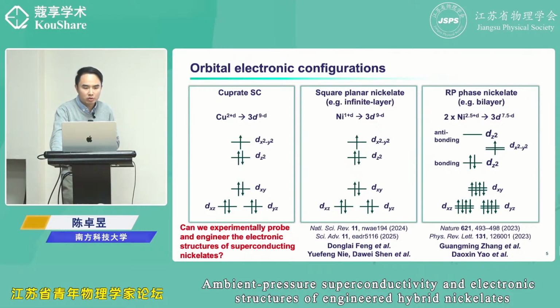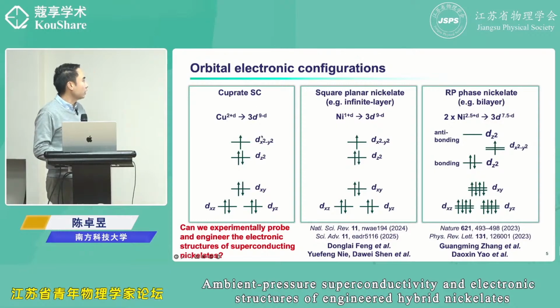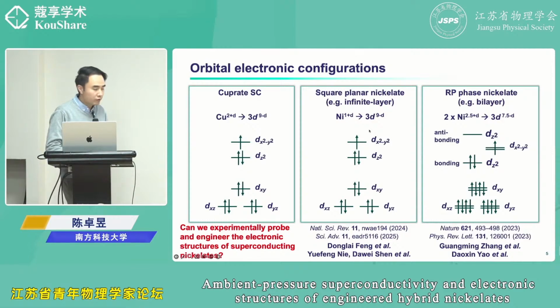Coming back to electronic structure, cuprate and the square planar nickelates are quite similar. This is 3d9, and you can see dx square minus y square is at the top. And square planar nickelate, take the infinite layer for example, it is also similar, but there are some difference mainly coming from the 5d orbital or the interstitial s orbital. But if you only consider this nickel orbitals, it's very similar to the cuprates.